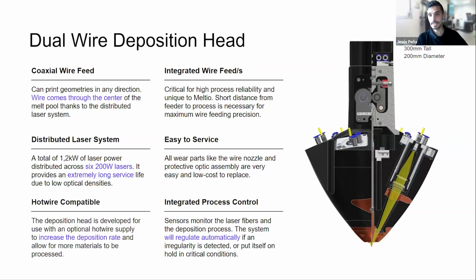In a print, you can be using one wire while the other is completely folded inside of the head. And as soon as the process of depositing this wire is done, you can retract it, and then continue with the other wire that is being fed. Like this, you can achieve the dual wire material prints that Michael was mentioning before. So layer by layer, you can have those 2 materials in several of the walls of the print, and then you can build the print up in the Z-axis direction, having those 2 materials in several points that you wish to.